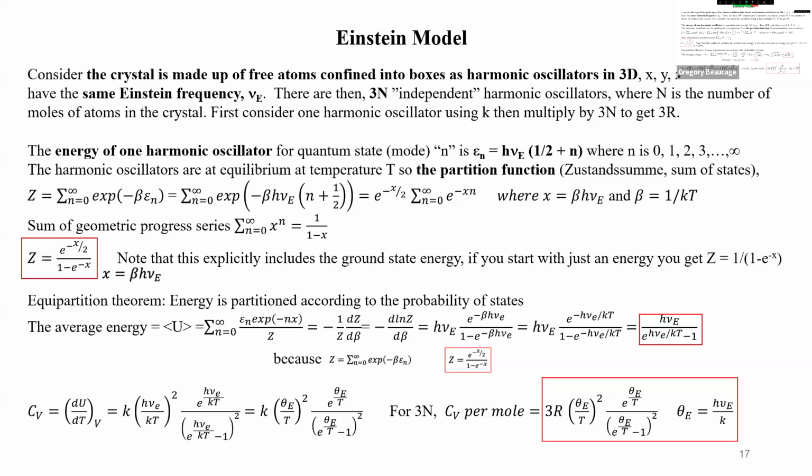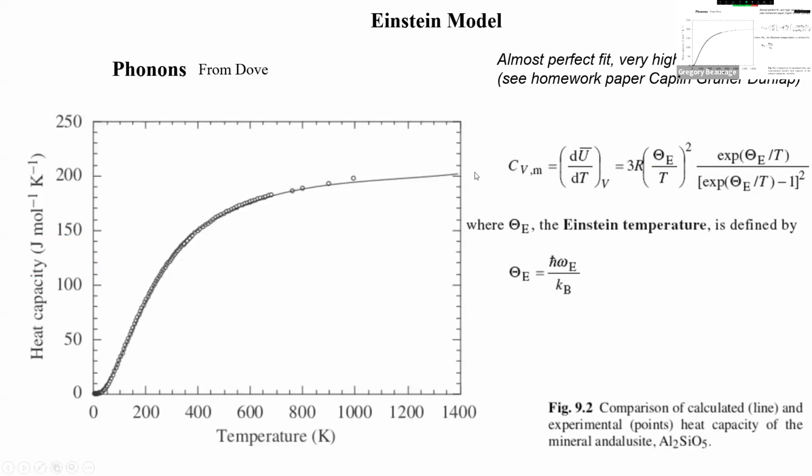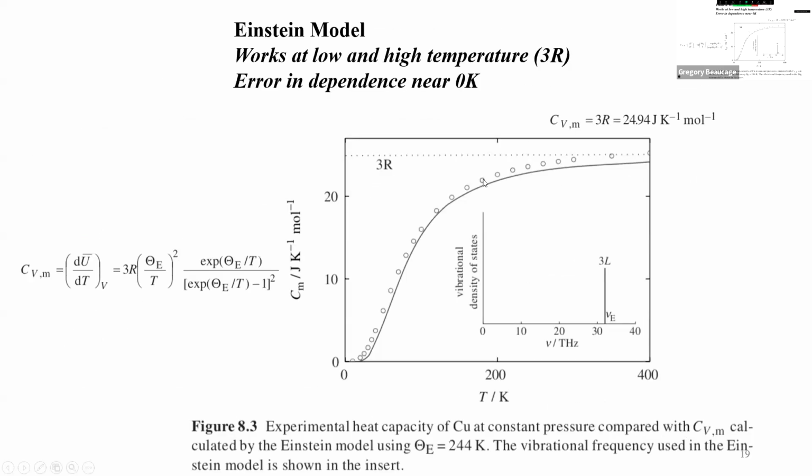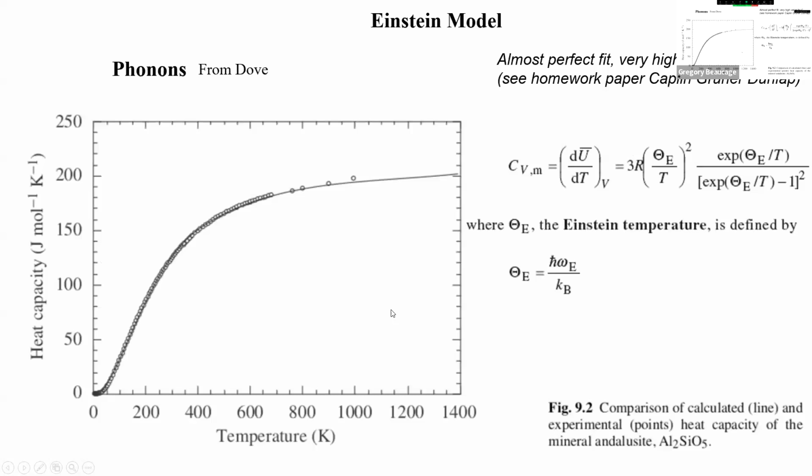So it's interesting. It would have a high heat capacity, compared to a normal heat capacity of like 20, right? So this is copper. It's got like 20 heat capacity, and a 244K Einstein temperature, right? And this thing, for this aluminum silicate, it's got 200, right? So it's 10 times more heat capacity because it has these open aluminum atoms floating around in the crystal, right?